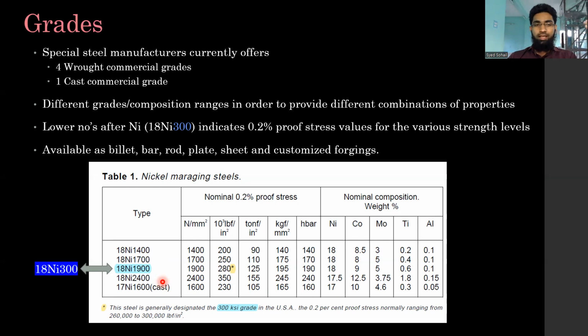So regardless, the point here to note is the lower number after nickel indicates the 0.2% proof stress value for various strength levels. So the strength level, either in KSI or Newton per mm square, basically megapascal, different units. But the point is, it indicates 0.2% proof stress. They are available as billet, bars, rods, plates, sheets, customized forgings. These are all general offerings. The different shapes or geometries that this material is offered from the commercial industry are such and such.